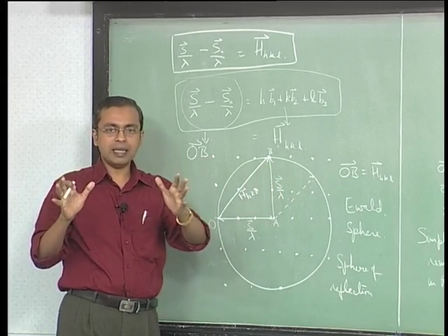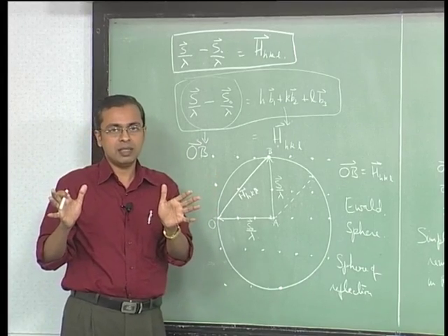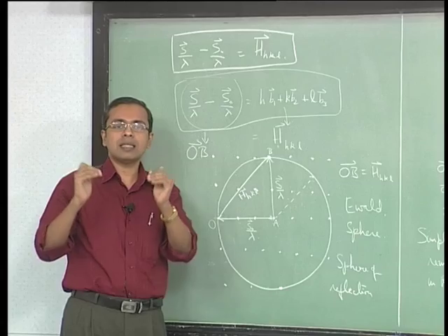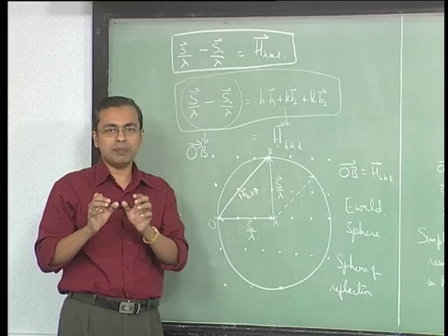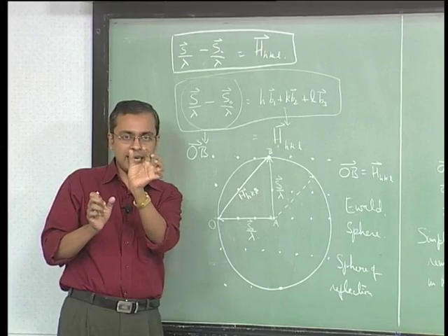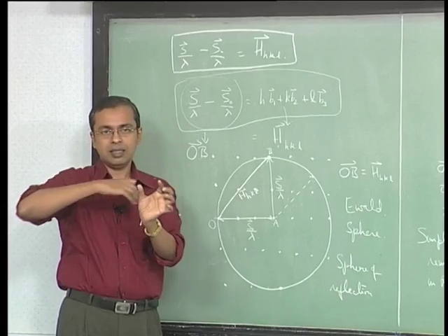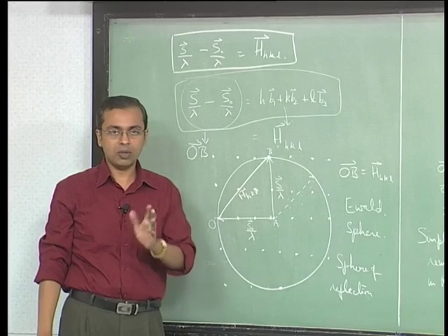This same material, if you want to understand how it is interacting with waves, especially electromagnetic waves, we will have to first represent this in reciprocal space. Its representation in reciprocal space will continue to be a simple cube, except that the dimensions will now be 1 by A. So you will make 1 by A, 1 by A and 1 by A in 3 directions, and you will build the lattice. That is the reciprocal lattice of the original material you are interested in.